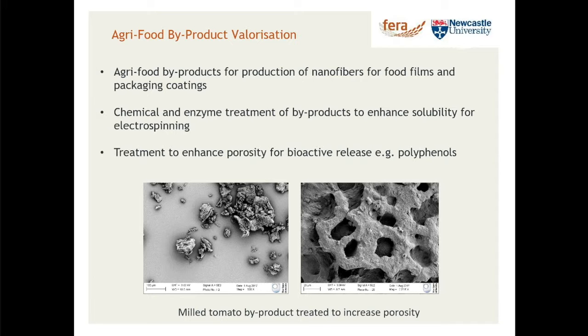So what we've got here is some images. On the left is some milled material, which is sort of micron sized. And then we can chemically treat this or enzymically treat it to try and enhance its porosity, so it will then more easily release some of the molecules that are present, such as these polyphenols. And so on the right, this is just an image of some more porous looking, in this case, tomato skins that are being milled, dried, and then treated with sodium hydroxide in this case. But ideally, we should be going towards all biological processes rather than using chemicals.